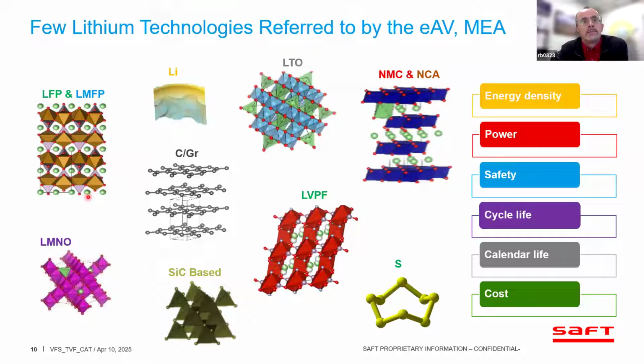We have the LFP, the iron phosphates. We have solid lithium electrodes. We have LTOs, lithium titanium oxide. We have NMC, nickel manganese cobalt, or NCA. So you have all kinds of chemistries, and you can see the crystalline structures here. This 3D structure is a solid metal. Here you have a lamellar structure. And carbon graphite here, LMNO, silicon-based carbon. Similar to this one here, or even more exotic, LVPF, lithium vanadium phosphate fluor technology, and you also have the sulfur that we can hear about.